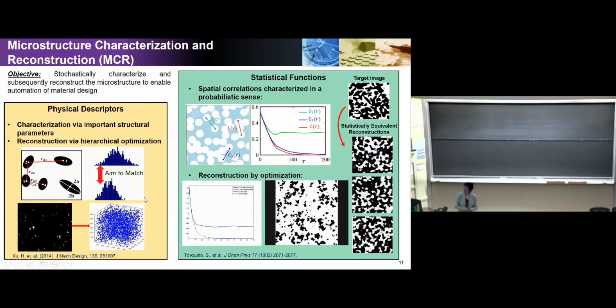So for design purposes, we actually proposed a descriptor-based method. The descriptor has some assumption of the shape of the particle, could be like an ellipsoid, right? And then you use certain parameters to represent the particle size, geometry, the dispersion status, and some other important quantities. This method is very fast. But on the other hand, it cannot model very irregular geometry.